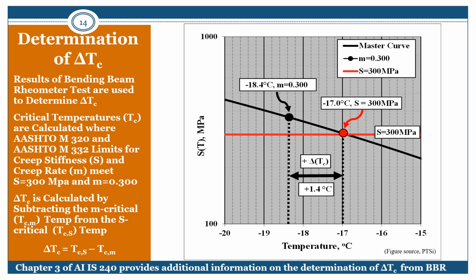This figure presents a graphic depiction of delta TC. This is where the M value, the temperature where M equals 0.300. This is where the S value is exactly equal to 300 megapascals. The delta TC is the differential between these two temperatures, or delta TC equals T sub CS minus T sub CM, which gives us the delta TC. In this case, the delta TC is a positive 1.4 degrees Celsius.